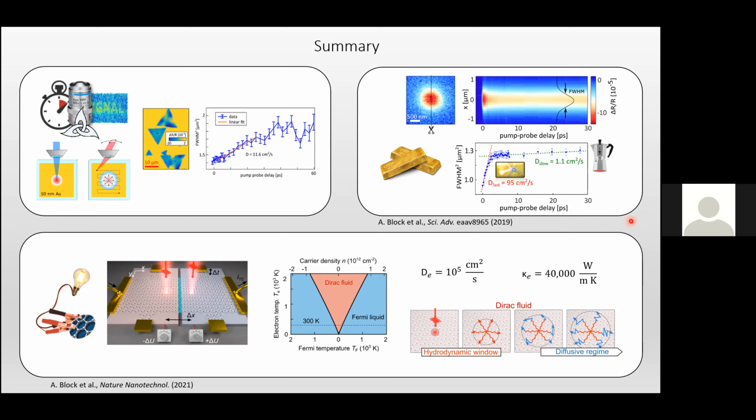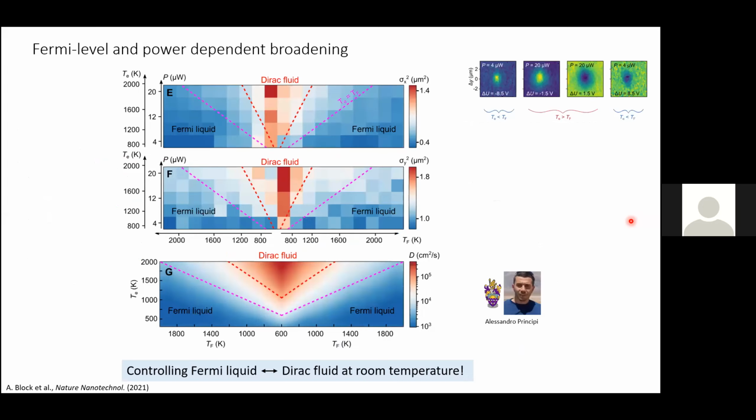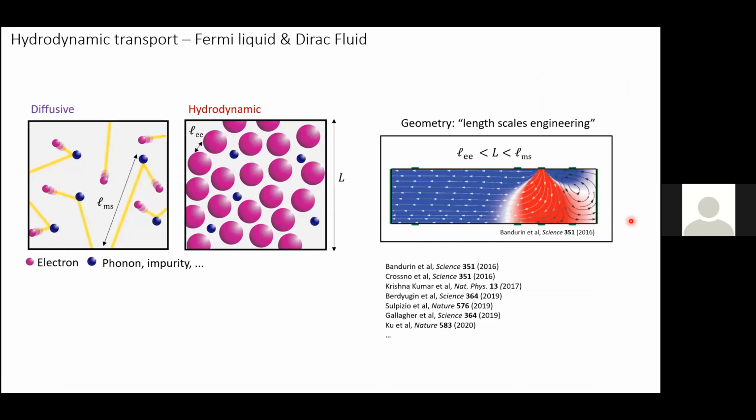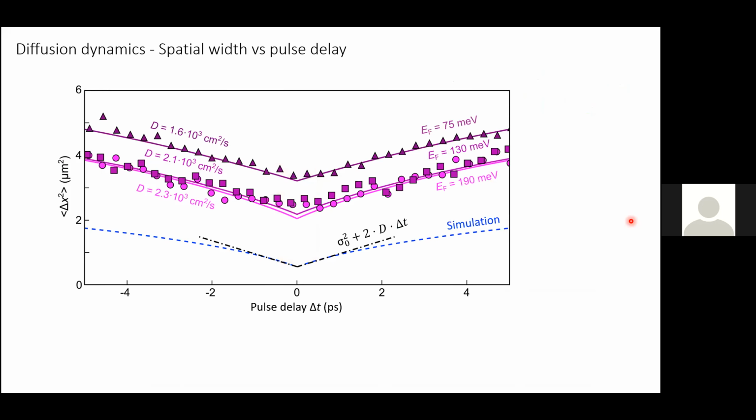I see. And one last question. So when you compared the measurement on bulk, was it silicon? Yeah. And molybdenum oxide, yeah? So what was the substrate for molybdenum? The molybdenum on glass. On glass, okay, thank you. Yeah, and actually the fact that the two numbers are so similar is a bit of a coincidence, because in this case of silicon, it just happened to be the doping of the wafer that we bought that made this number match to about 12 centimeters squared per second. Yeah, and the molybdenum was on glass.